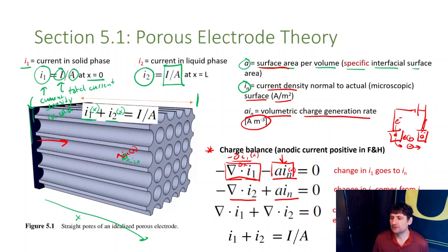And this is essentially saying the same thing: in the 2-dimensional electrode case, I have to convert all the electronic current into ionic current, and I have to do that at the 2-dimensional boundary. But in a porous electrode, I can convert part of the electronic current to ionic current at different x positions in the electrode. And that's exactly what these 2 equations are saying. They're telling me how the change in current in the solid or in the electrolyte as a function of position depends on the interfacial current, which is communicating between the 2 phases. It is the rate at which electrons are transferring from one phase to the other.